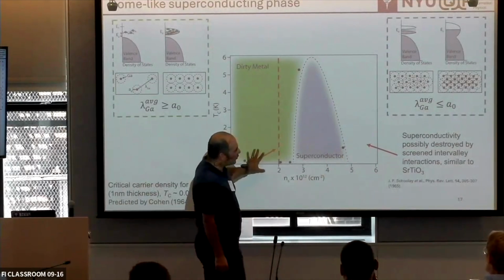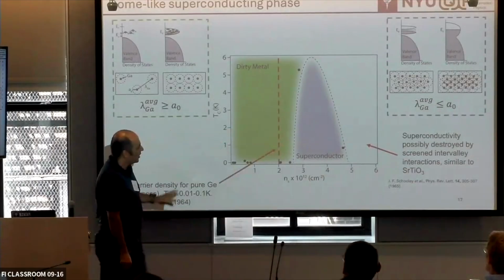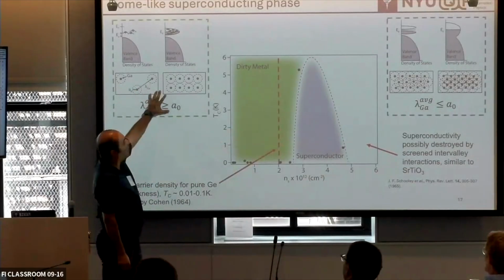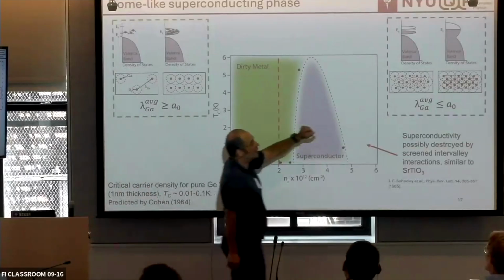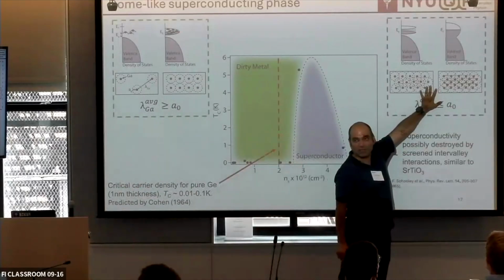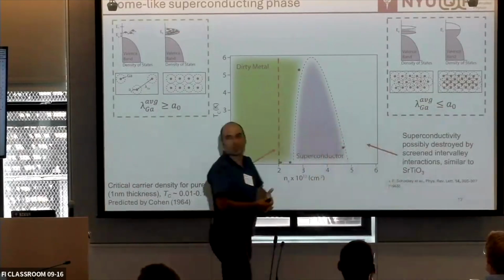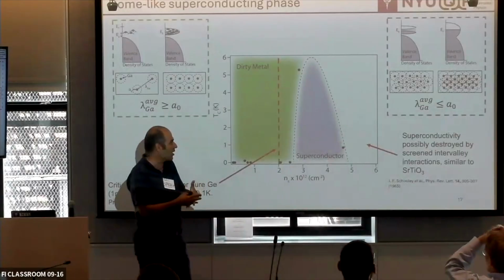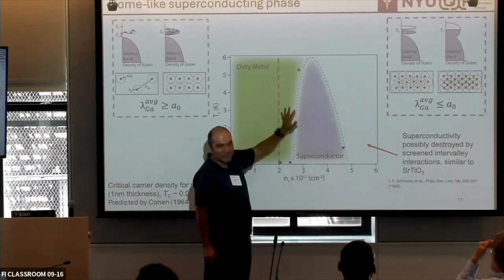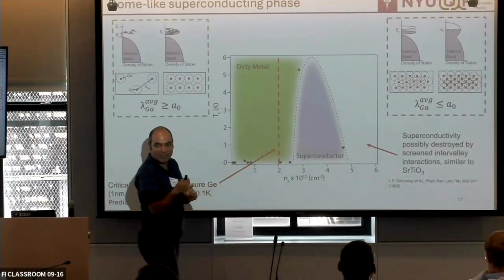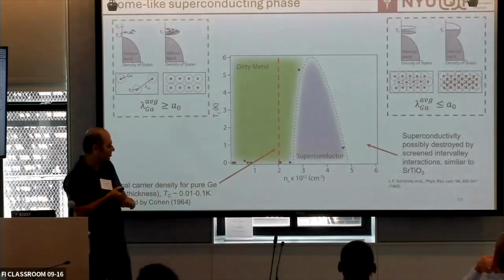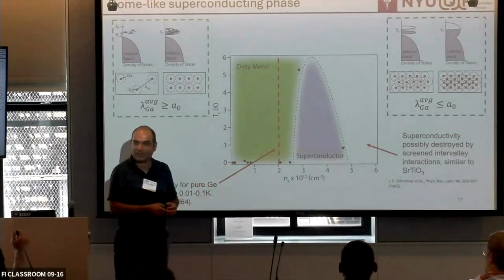But the state of the art when we did that experiment was that look, whether you don't have enough doping, that basically things are not superconducting, or you have too much disorder, you have too much that basically now you are destroying superconductivity. So if there is a superconductivity, you want it to be in the middle, you want a lot of electrons, and it should be electron-driven superconductivity, basically.